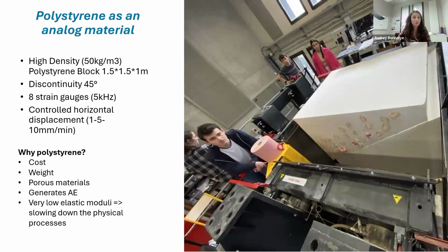Our idea is to try to do something a bit similar in our machine, and we've done some very preliminary tests with the students, and I'm using all of the students here to help me carry those blocks that are very heavy. So we decided to do those experiments on polystyrene. On high density polystyrene, so the density is 50 kilograms per cubic meter. It's the highest density polystyrene that I could find on the market, and on those very large blocks. So this time we're almost entirely filling the machine. We made a discontinuity in our material, and we placed some strain gauges along the interface in order to see whether we could measure something.